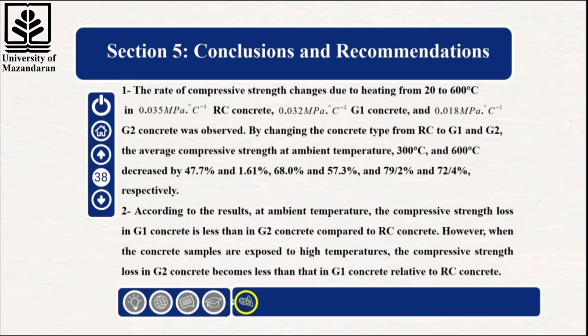2. According to the results, at ambient temperature, the loss of compressive strength in G1 concrete was lower than that of G2 compared with RC. However, at elevated temperatures, the reduction in compressive strength relative to RC was smaller in G2 compared with G1.